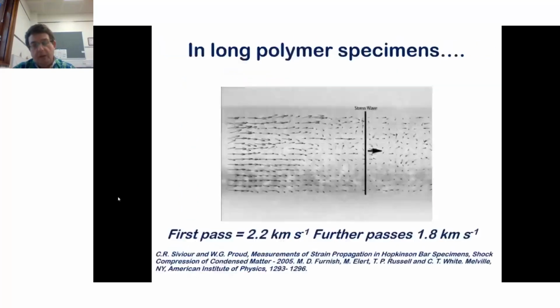How does stress move? How does the stress speed move through the sample? In this case, for long polymer specimens, it was discovered that on the first pass, the wave speed was quite high, but it slowed down on subsequent passes because the first pass through that polymer sample was affected very strongly by inertia. And the inertia made the material not want to move laterally, which meant the energy had to go along the sample. And because the energy is going along the sample, that means that the wave speed we see is higher, because wave speed, sound speed, is related to the amount of energy you put into the wave.